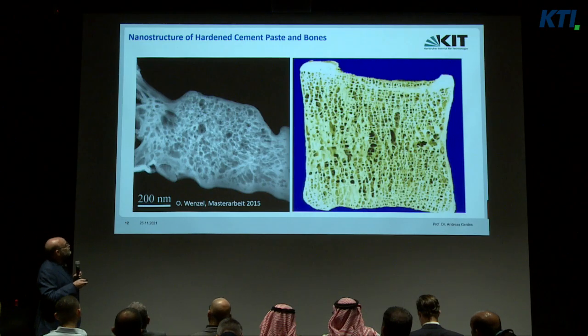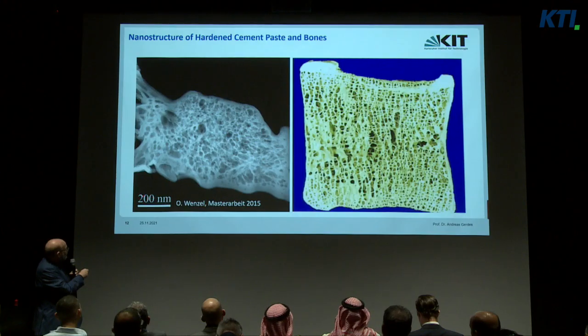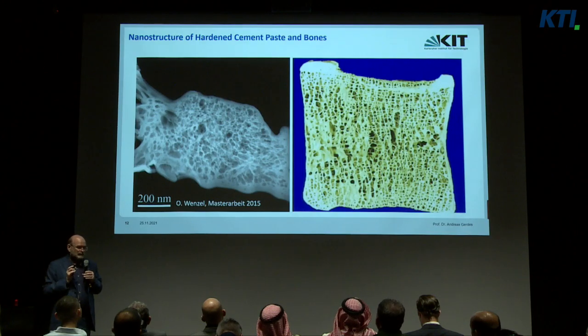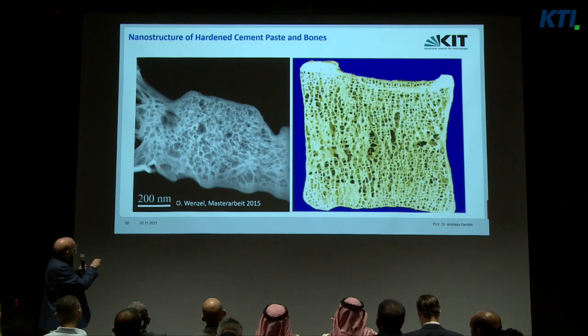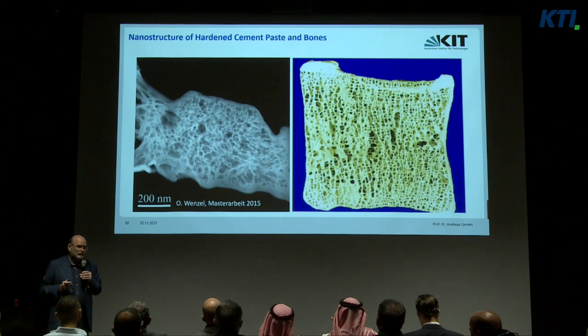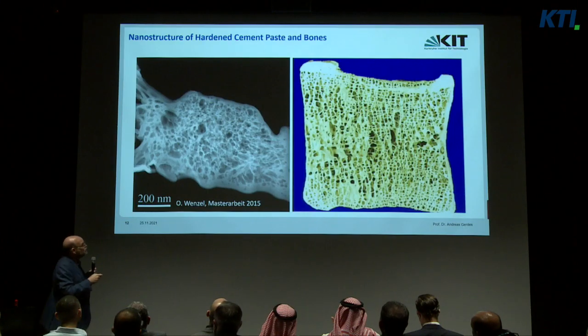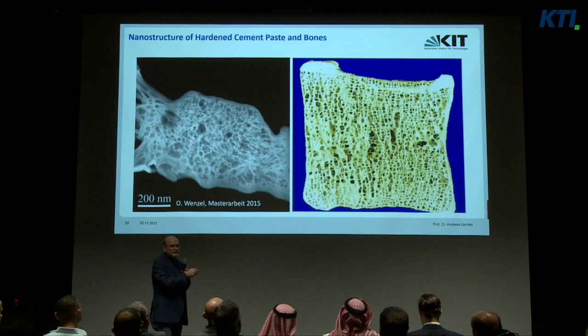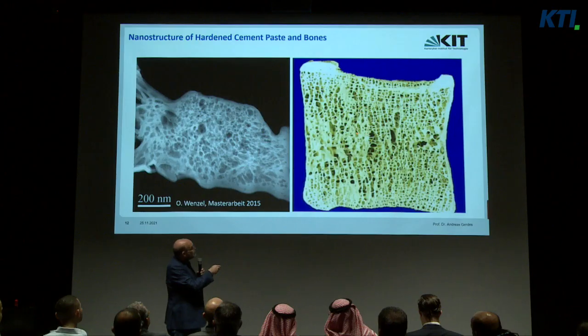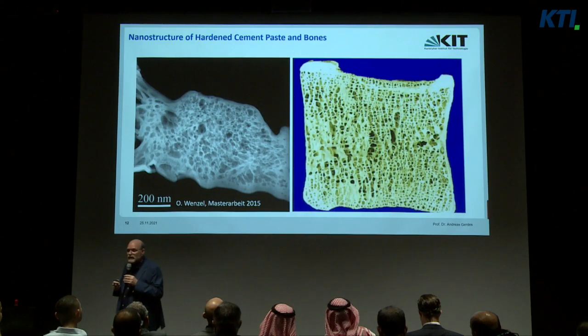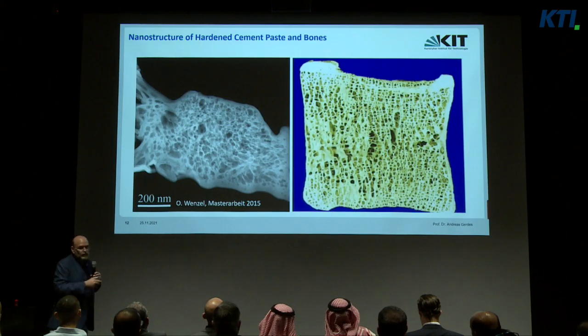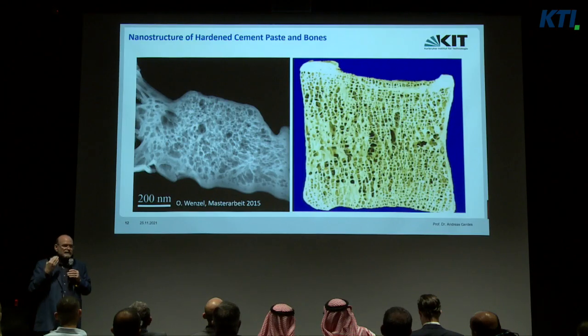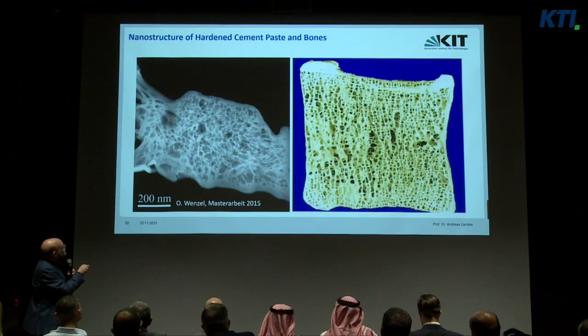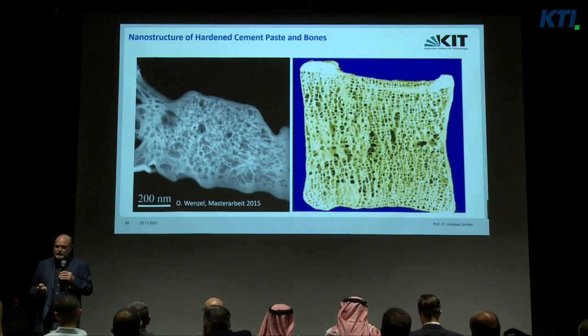And if we have a look at the next one, this is at 200 nanometers magnification. And this is the cement-based material I have shown in the figures before. And if you compare it to that, this is a bone. So that means the porous structure of a bone is very similar to the porous structure of our cement-based material. And that's the reason why we have to take care not to damage the bones of our concrete structures.